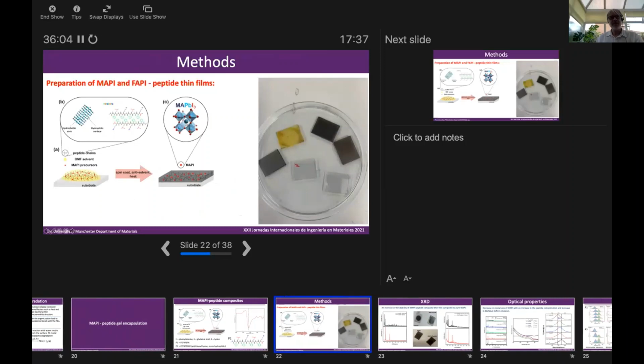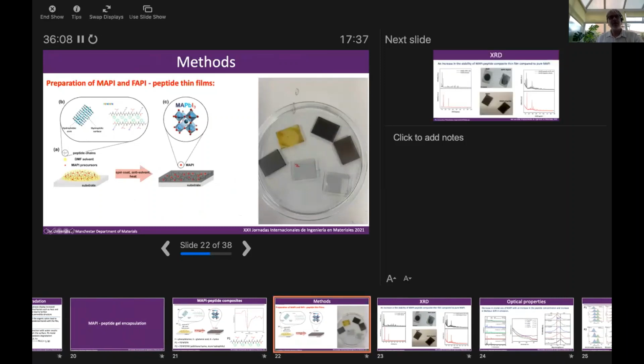Well, the first thing we did, we started with a single peptide gel, the one without the additional lysine. We mixed it with methylammonium lead iodide and also with formamidinium lead iodide. These are the two pure materials with no peptide: this is pure MAPI, methylammonium lead iodide, and this is FAPI, formamidinium lead iodide. When we add the peptide, the methylammonium lead iodide is fine. It makes quite a nice film, but the formamidinium lead iodide won't actually form the perovskite.